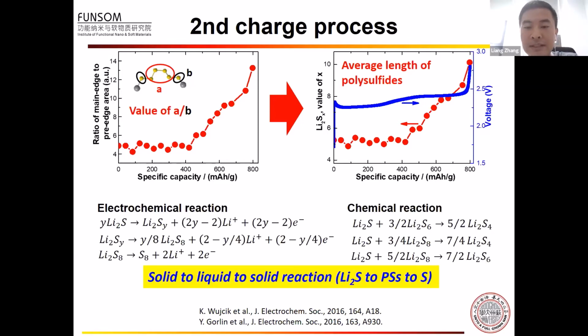Because of the presence of lithium polysulfide, two reactions can happen simultaneously. One is the electrochemical reaction, which can result in the increase of the average length of lithium polysulfide. The second is the chemical reaction, which can result in the decrease of the average length of the polysulfide. These two reactions come to a balance at the beginning of the second charge process. Therefore, the average length of the polysulfide doesn't change very much at the beginning. With the charge process going on, the electrochemical reaction becomes dominant. Therefore, the average length of the polysulfide increases.